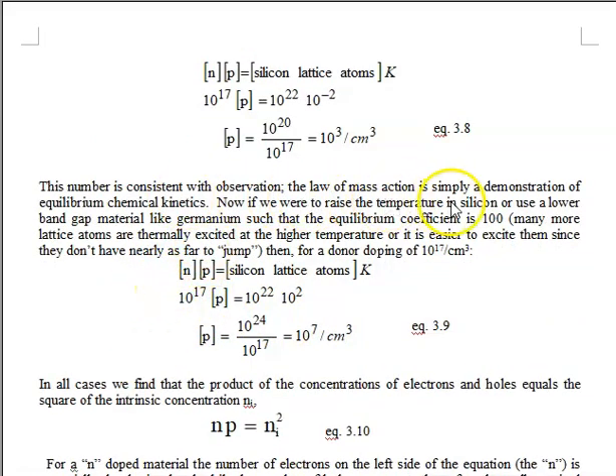Now, let's say we raise the temperature so that the equilibrium coefficient, reaction coefficient, is not 10 to the minus 2, but 100. We could do that by, for example, raising the temperature to probably about 400 or 500 degrees Celsius. So many more lattice atoms are thermally excited, and then we still put in the same 10 to the 17th for the mobile electrons. So now we have 10 to the 17th mobile electrons.